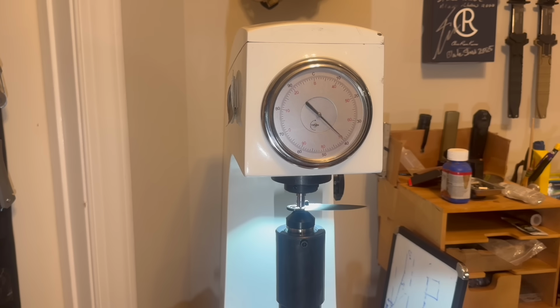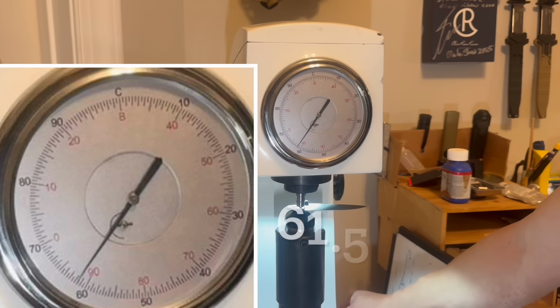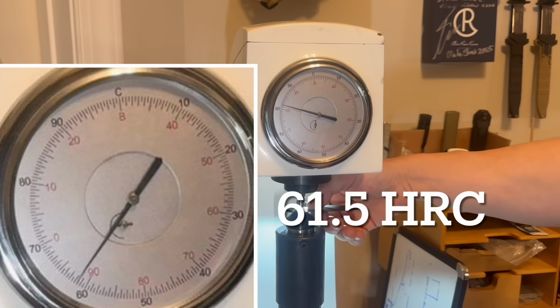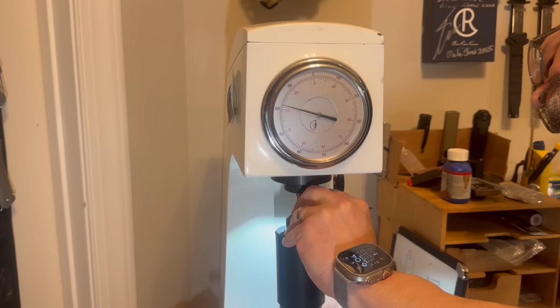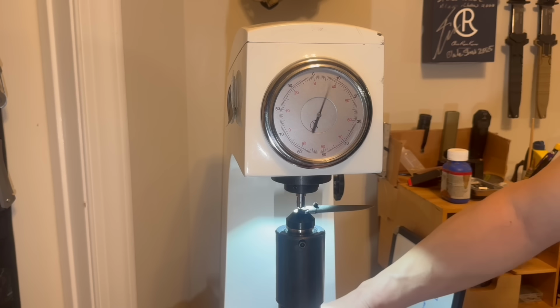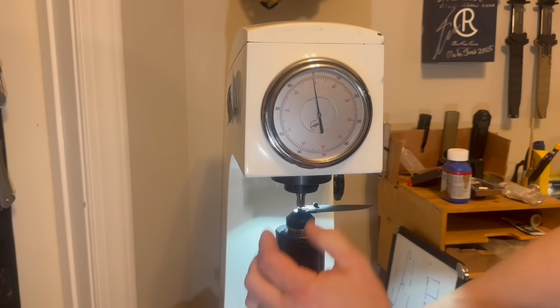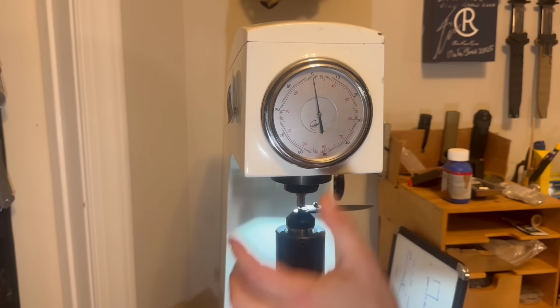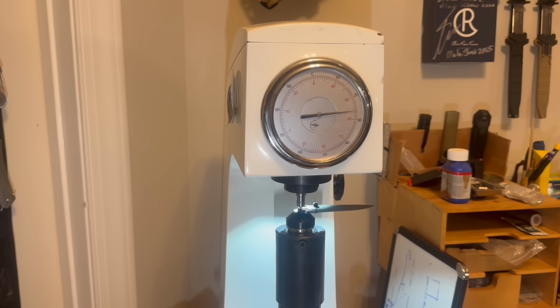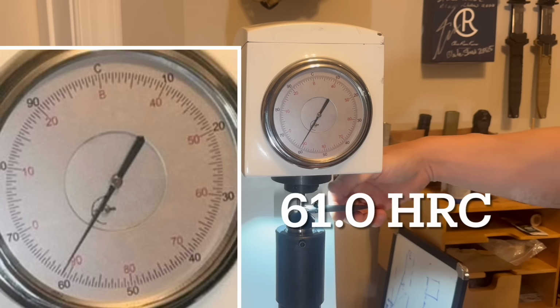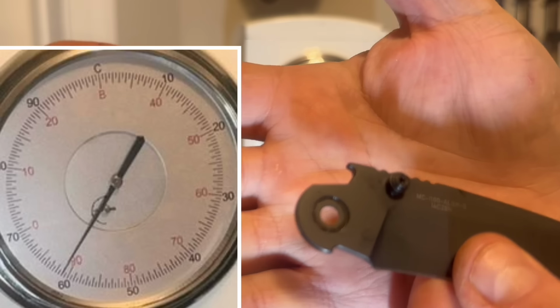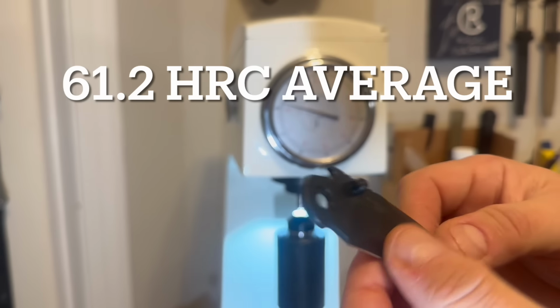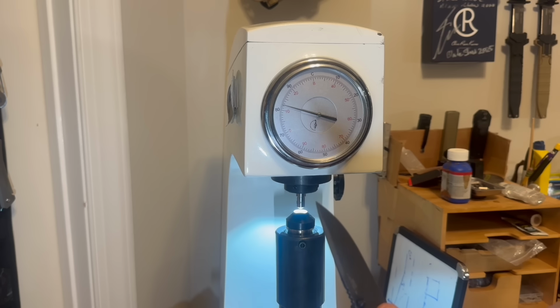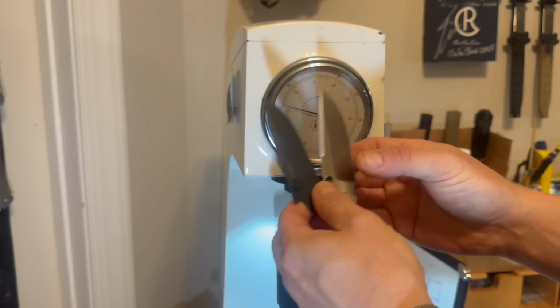And PVD coating, which stands for Physical Vapor Deposition, is better than Cerakote because it only requires 40 minutes to an hour and a half at 300 Fahrenheit. And by the way, it gives you more scratch resistance than the Cerakote. But even there's some risk to soften the blade below desired range. So a manufacturer has to pre-plan for that and heat treat to a higher hardness before coating. And then they can hope to get into this perfect range. Right here it's 61.0 again, for the average of 61.2 HRC. So for these two blades, the heat treatment was done to the best world-class standards.